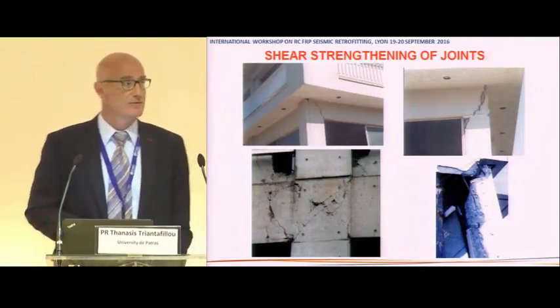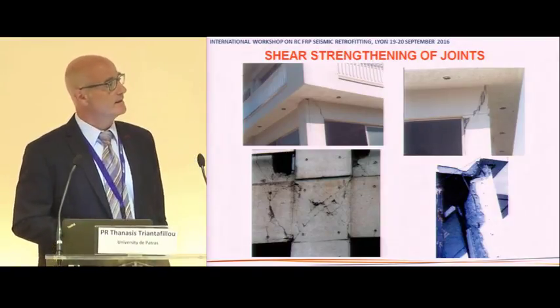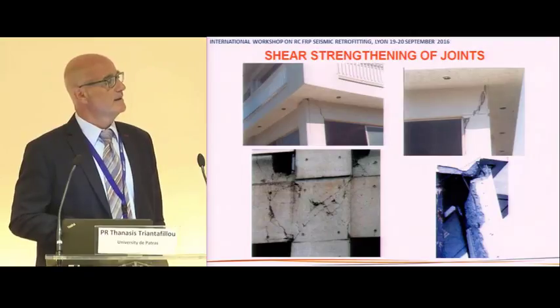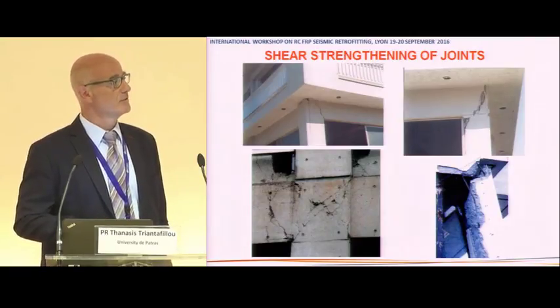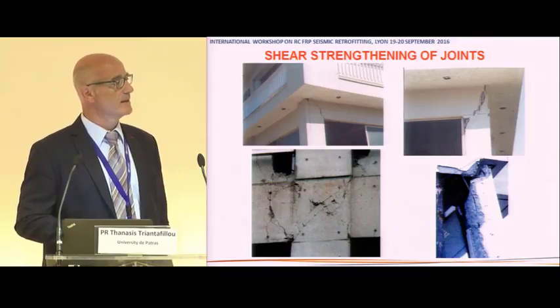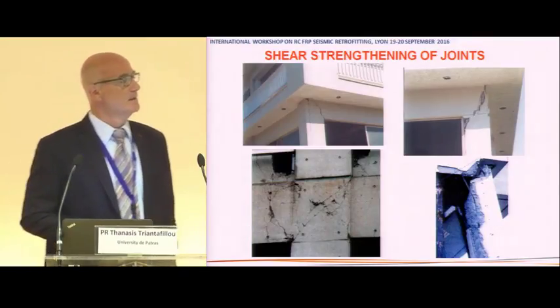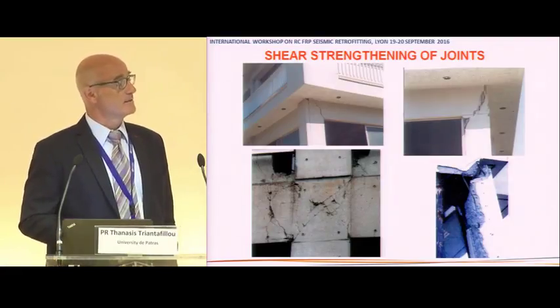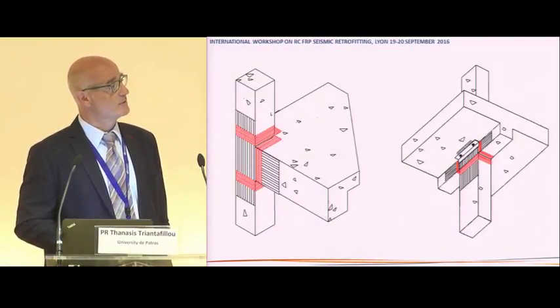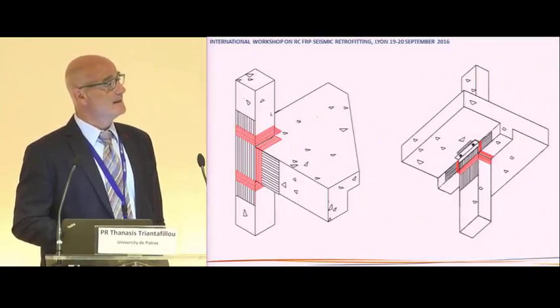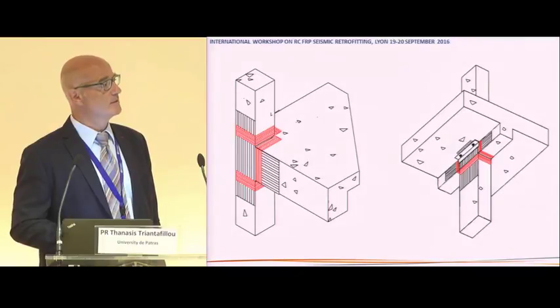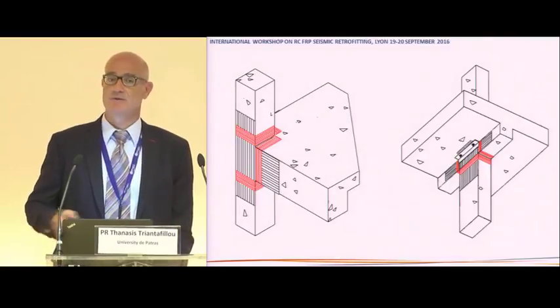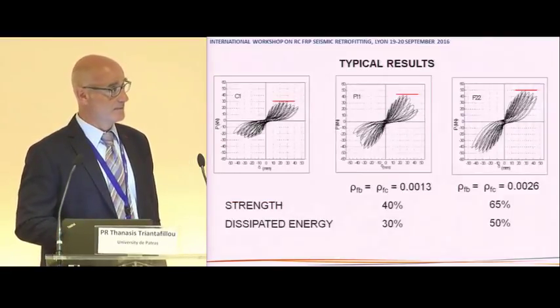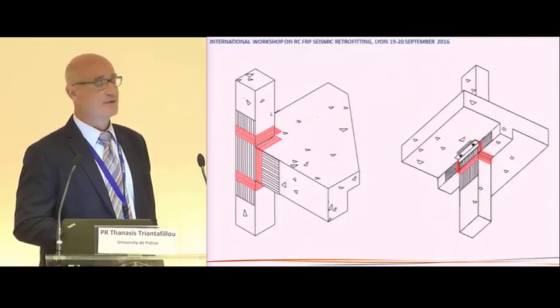Shear strengthening of joints, that was very nicely covered by Maurizio this morning. That's a very tricky area here. We typically get shear failures in joints due to the lack of continuous stirrup type reinforcement in those elements. And one way of shear strengthening the joints is through the application of FRPs. Ideally, we should place the fibers in two directions here, both horizontally as well as vertically. If we choose one of the two methods, the horizontal configuration is preferable, but ideally we should do both.